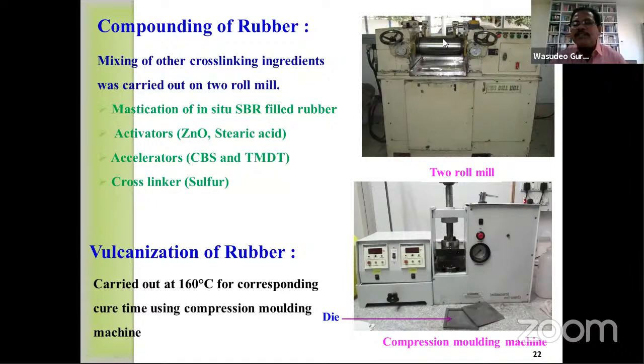We have to take that mixture and put it here. And there is some 10-ton pressure. After setting the temperature and the pressure, these 2 rolls are moving, and when we put the solution, we get the rubber sheet. The rubber sheet obtained in this case is a rough sheet, so we have to finish it by pressing, using the hydraulic press here.